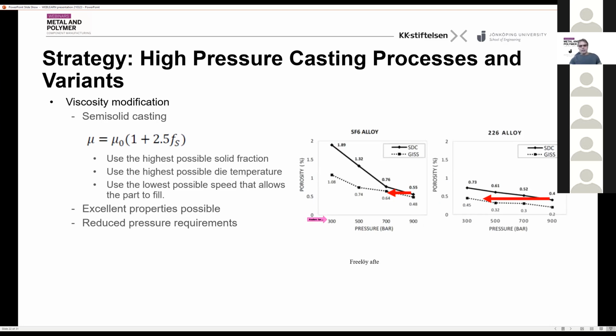Now, looking at this, there are some additional advantages. If we set 0.5% here as porosity, and you compare conventional high integrity casting with Rheocasting, combining all the possible means, yes, using vacuum and high pressure die casting, Rheocasting and vacuum. And this is the end pressure of the machine, the intensification pressure at the end of the fill. You can see that in order to reach this 0.5%, you need a lower end pressure for Rheocasting, which is the lower line, than for the upper line, which is conventional casting.